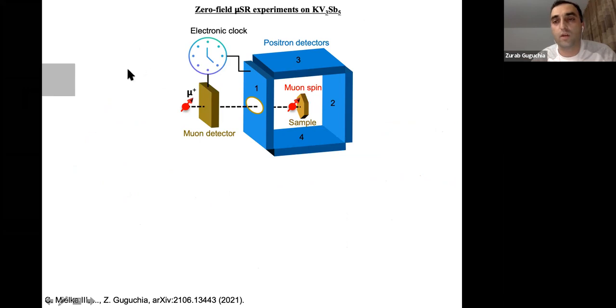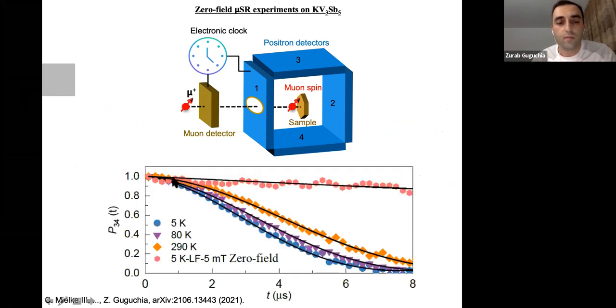kagome metal to look for any weak static or dynamic or fluctuating magnetism in the material. So this is the muon spin polarization as a function of time. And you see that there's no oscillation because we don't have long range order, but you clearly see there's some temperature dependence of the relaxation rate.